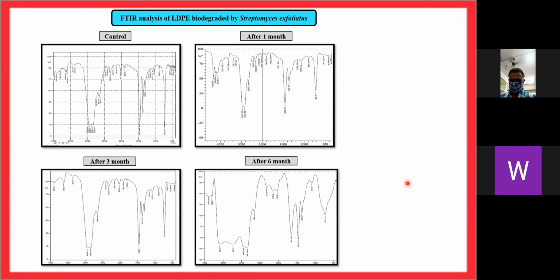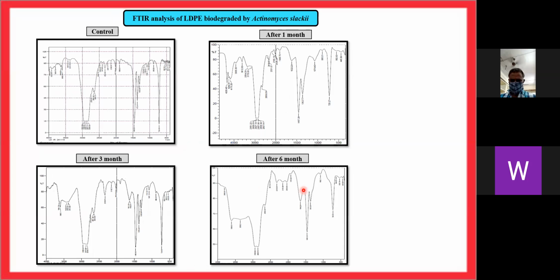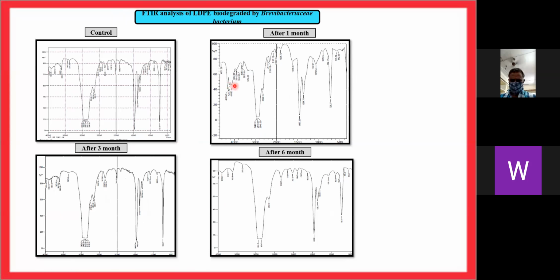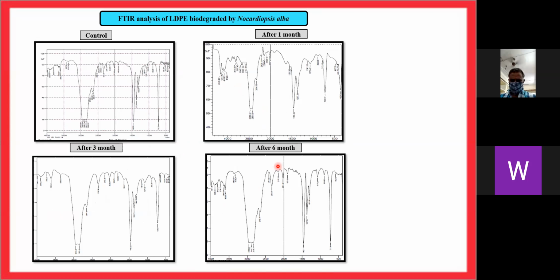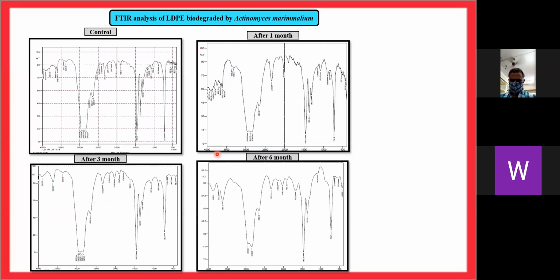This slide shows the FTIR graph of LDPE biodegraded by Streptomyces exfoliatus. It is in the case of control and after 1, 3, and 6 months. We can see the formation of new functional groups and disappearance of a few functional groups. This is in the case of Actinomyces slackii. This is in the case of LDPE biodegraded by Brevibacteriaceae bacterium. Notable changes were observed. This is in the case of Nocardiopsis alba. You can see appreciable changes after 6 months compared to control. This is in the case of Actinomyces marimmalium.